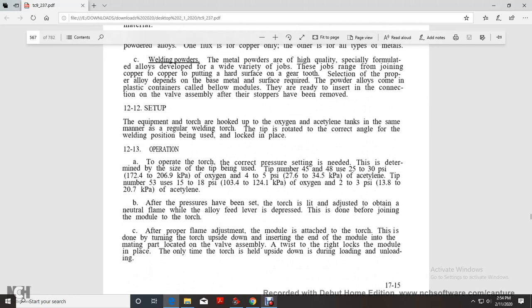12-12 Setup. The equipment of the torch is hooked up to the oxygen and acetylene tanks in the same manner as a regular welding torch. The tip is rotated to the correct angle for the welding position being used and locked in place. Operation. To operate the torch, set the correct pressure, determined by the size of the tip being used. For tip number 45 or 48, use 25 to 30 psi oxygen, 4 to 5 psi acetylene; for the smaller tip, 15 to 18 psi oxygen, 2 to 3 psi acetylene.